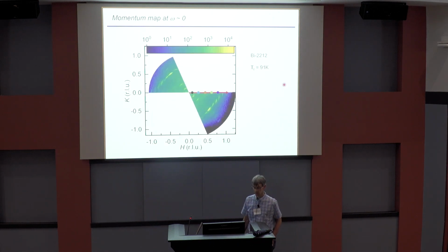This is a zero frequency momentum map using surface EELS of bismuth 2212. This is the analog of a Fermi surface plot in ARPES. Basically what you do is you look at zero frequency, that's elastic scattering, and then just scan in momentum space to see where all the Bragg peaks are. And you see some things that you expect. There are a lot of reflections in BISCO because it has a supermodulation, and so these are all the supermodulation peaks.